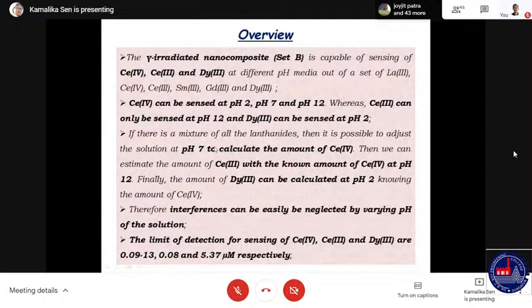If there is a mixture of all the lanthanides, is it possible? Yes, then it is also possible to adjust the solution to pH 7 to calculate the amount of cerium 4 first. Then we can estimate the amount of cerium 3 with the known amount of cerium 4 at pH 12. Therefore, interferences can be easily neglected by varying the pH of the solution.